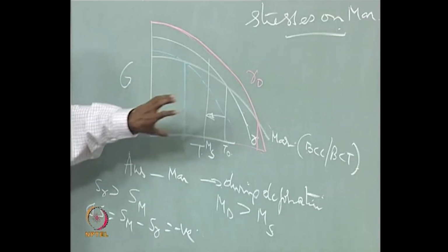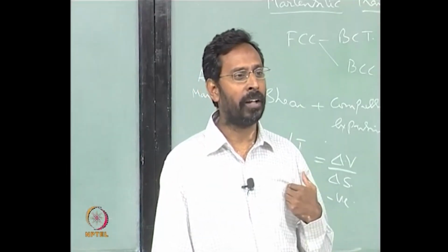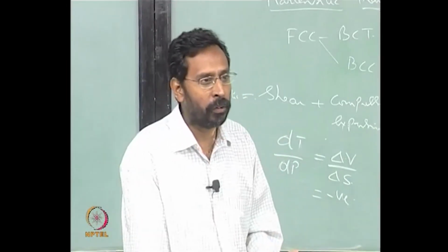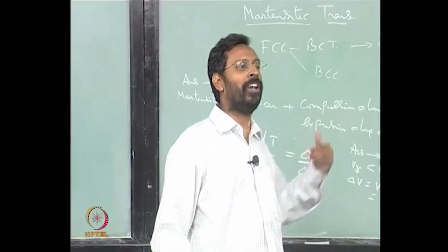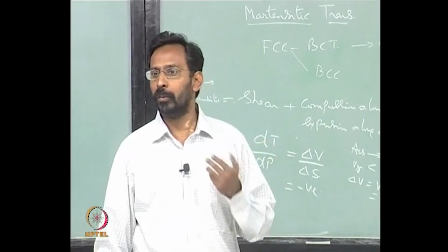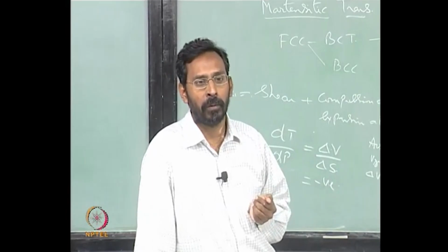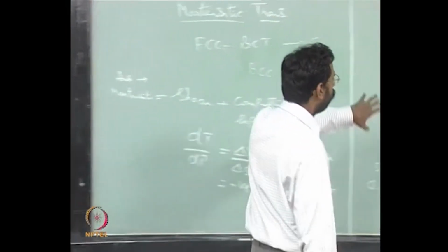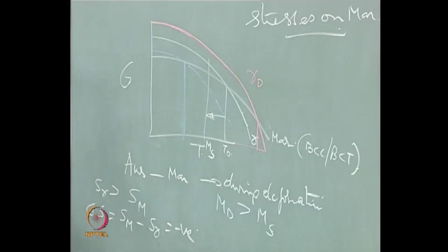Okay. So in case you are dealing with powders and doing HIPing or SPSing of them, and trying to see whether you get a martensitic transformation, you may say why should I bother about what temperature it will transform. I need to bother because I need to know to what temperature I should bring it if I want to get 100% martensite. So if MS itself is low, MF will also be low. So to get 100% martensite, you need to go to a much lower temperature, sometimes maybe even sub-zero. That is an aspect you need to understand. So the pressure brings in this effect and that changes the free energy, and as a result the whole transformation changes.